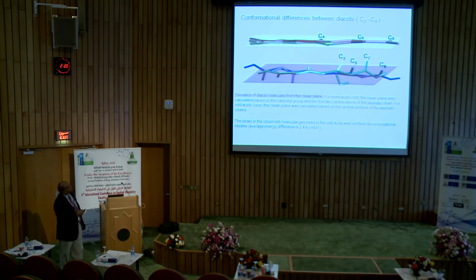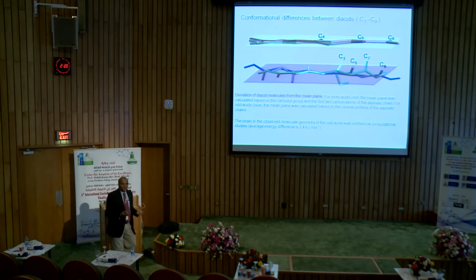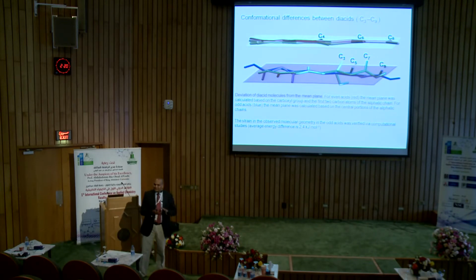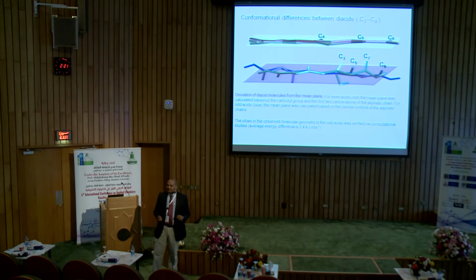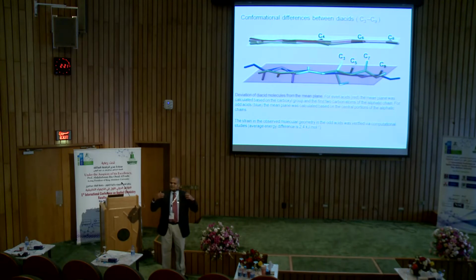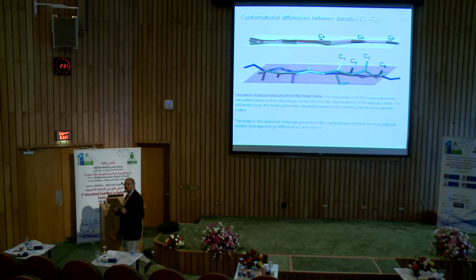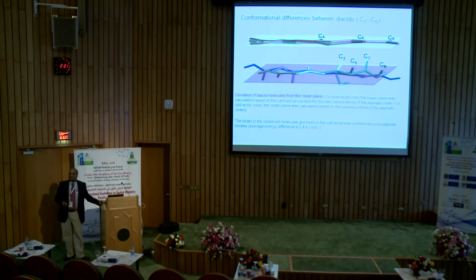So if you look at the chains in the even ones, C4 or C6 or C8, they're all planar. On the other hand, if you look at these odd ones, C3, 5, 7, 9, you see these extra bonds sticking out. So the way I would like you to visualize it, suppose you are traveling, if all your clothes are ironed nicely, you can pack them very easily, right? On the other hand, if they are not ironed, they're all crumpled and whatnot, you can still pack those clothes in the suitcase, but you have to really push them very hard. So the odd ones are like that. You have to really strain them to put them in the matrix.